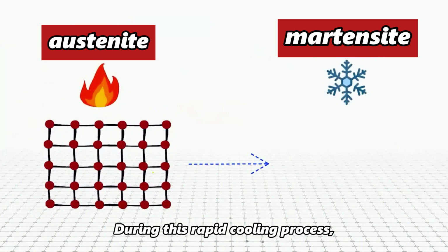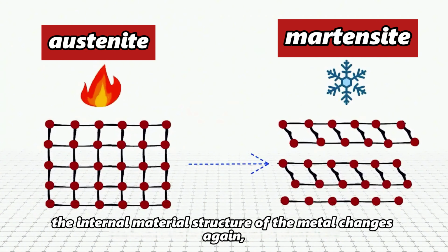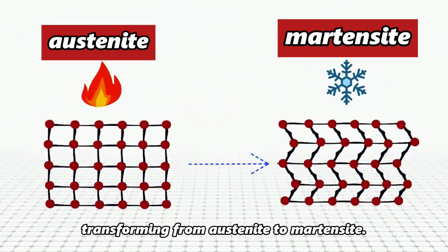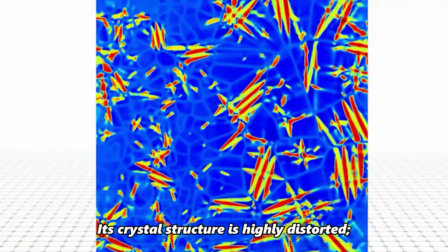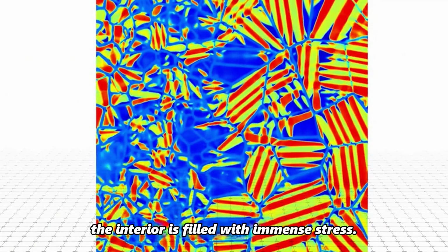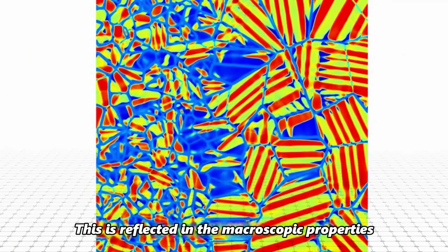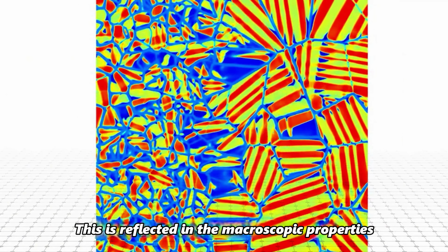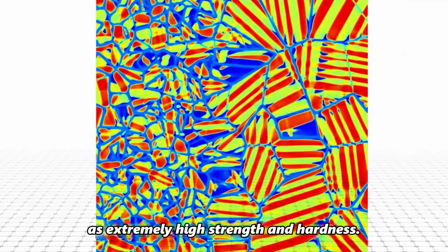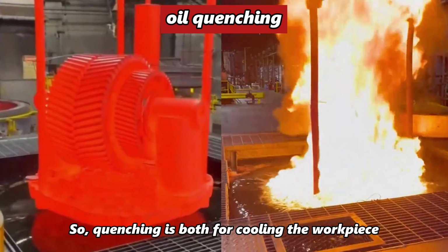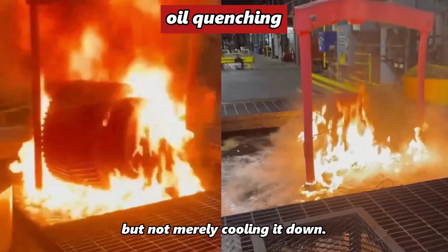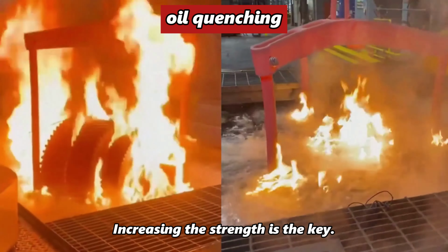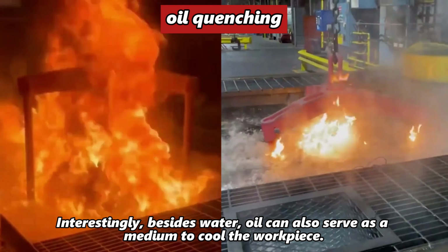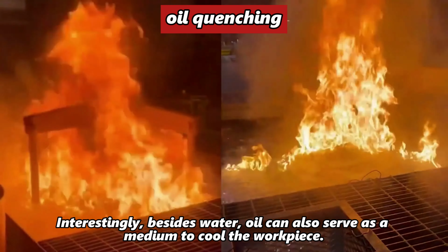During this rapid cooling process, the internal material structure of the metal changes again, transforming from austenite to martensite. Its crystal structure is highly distorted. The interior is filled with immense stress. This is reflected in the macroscopic properties as extremely high strength and hardness. So, quenching is both for cooling the workpiece, but not merely cooling it down. Increasing the strength is the key. Interestingly, besides water, oil can also serve as a medium to cool the workpiece.